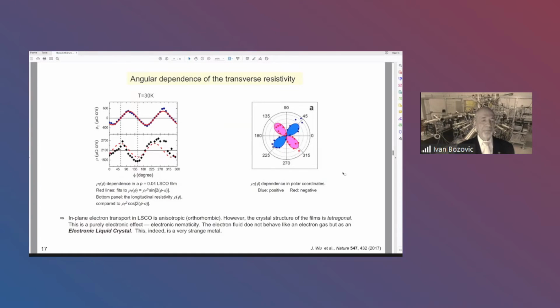Now, as you can see here, as a function of in-plane orientation, both the transverse and longitudinal resistivity show oscillations with 2 periods, 4 nodes. In the upper panel, the solid red curve is the fit of the experimental transverse resistivity data to the function A times sine of 2(θ minus α). But in the lower panel, the broken red curve is not an independent fit. What I did is just translate the top red curve down and to the left by 45 degrees. So the amplitude of oscillation in longitudinal and transverse resistivity is the same, while the phases are shifted by 45 degrees, as our little theory predicted.